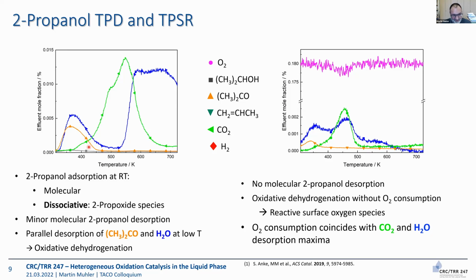Here, there's no oxygen in the gas phase. It's a TPD experiment. And then when we go up to higher temperatures, then of course we get a lot of CO2 and water. So that means we have proven it's this oxidative dehydrogenation. You don't even need the gas phase oxygen for that. But of course, when the surface oxygen is consumed at higher temperatures, then you have a totally unselective system.